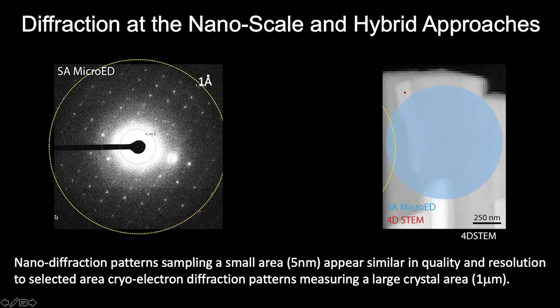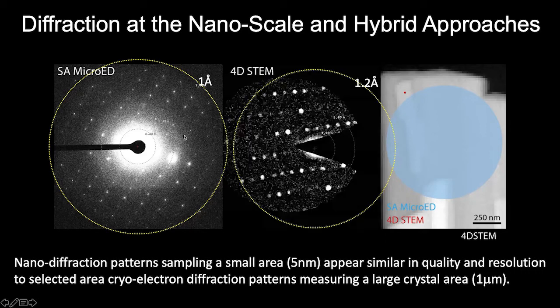So this is the conventional diffraction. We're getting a diffraction pattern in a selected area electron diffraction. And you can see that there are high resolution features in this diffraction pattern that extend out to about 1 angstrom in resolution. And by comparison, the diffraction is weaker from the small illuminated area, but we're still able to get regions of constructive and destructive interference. We can still identify a regular order to the diffraction patterns that is related to the lattice structure at that point in space.